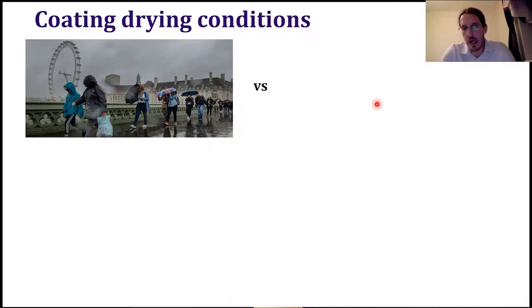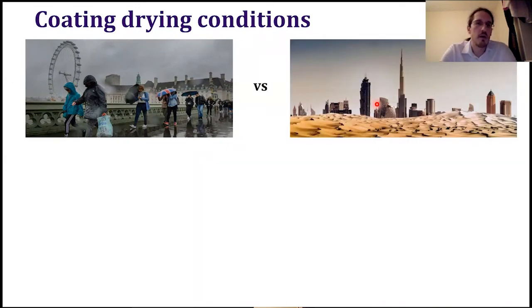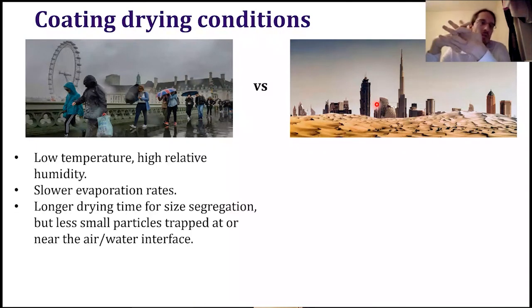Whether you are in a lovely day in London, raining and fog and wind, or if you are in Dubai in a really dry environment. If you are in the very wet and humid, so you have low temperature, high relative humidity, that means that it will evaporate much slower. And basically you will have more time for size segregation, but at the same time, this process where the particles get kind of trapped at the top while they're drying will happen less often. So it might also weaken this stratification process.